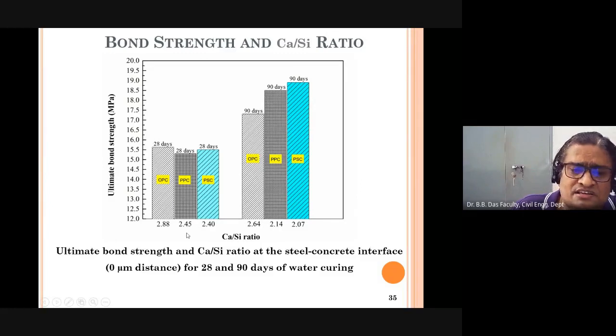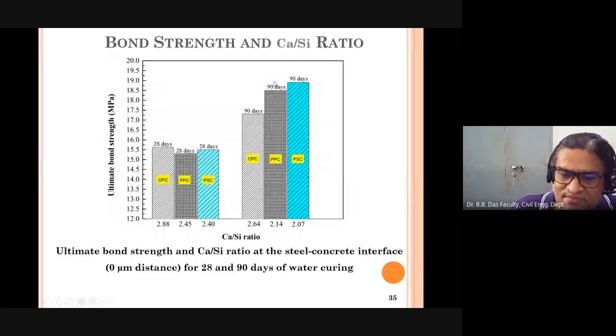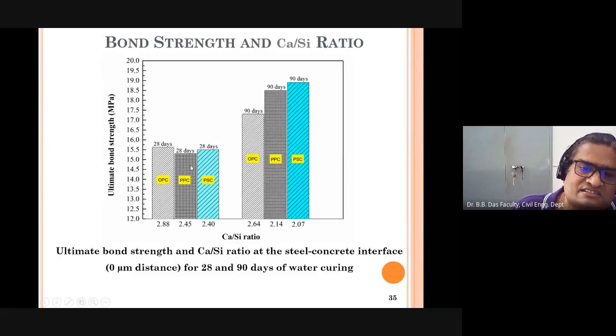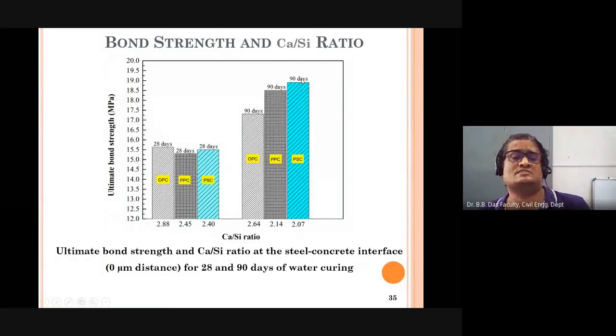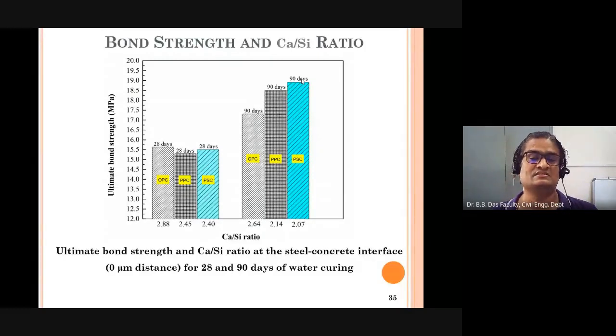It is natural actually. At 90 days, the calcium silica ratio is getting lesser, and that is indirectly saying the ultimate bond strength is also higher. So there is a trend actually. There is a uniform trend, but at 28 days there is no trend. At 90 days you can see there is a trend. That is what is showing the ultimate bond strength and calcium by silica ratio.